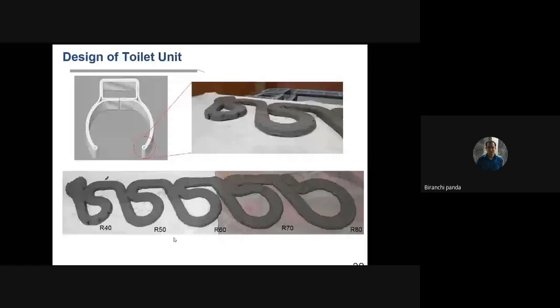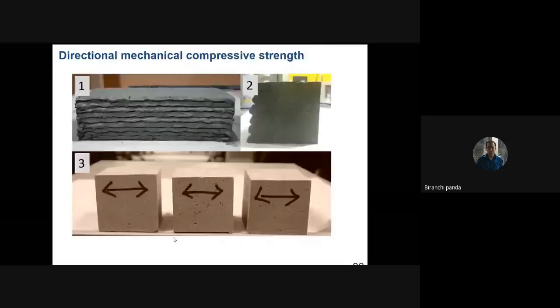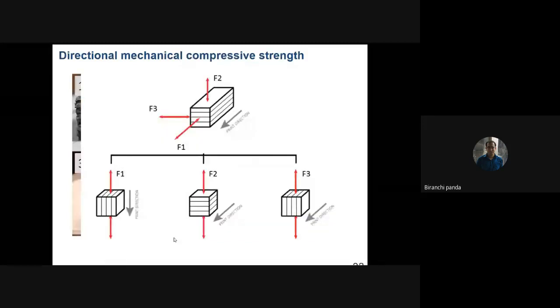And finally, when you print everything, we have to go for mechanical property testing. In 3D printing, as you know, the parts that are produced are not isotropic, they behave as anisotropic. It means that they will have different properties in different directions. So to confirm that, we printed the sample and collected different cubes, because these are the standard cubes for testing of compression. We extracted the cubes and applied forces in three different directions: F1, F2 and F3. As you can see, those loads have been applied in three different directions.